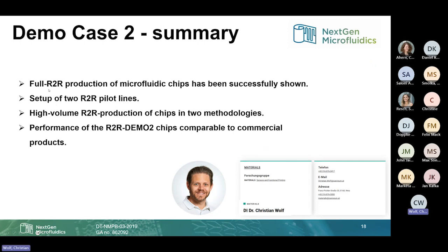So I think we could show in the demo case that the full roll-to-roll production of microfluidic chips is possible, and that it's really a high volume roll-to-roll production of those chips. And 2 distinctive pilot lines were established. One for this UV imprinting, where UV means UV light cured resin, and NIL is nano imprint lithography, because as I said, you can go down to the nanoscale of your structures. That was not needed in the demo case, but it's possible. And the performance of those roll-to-roll demo chips is comparable to the commercial products.